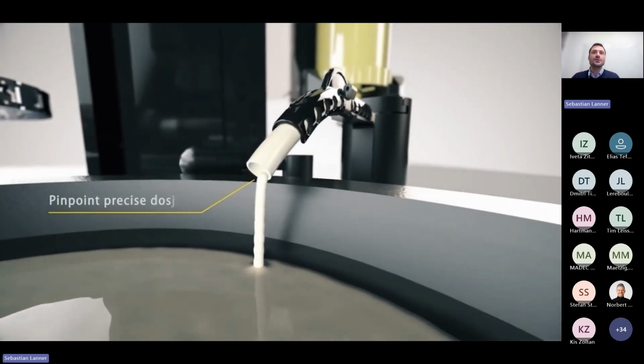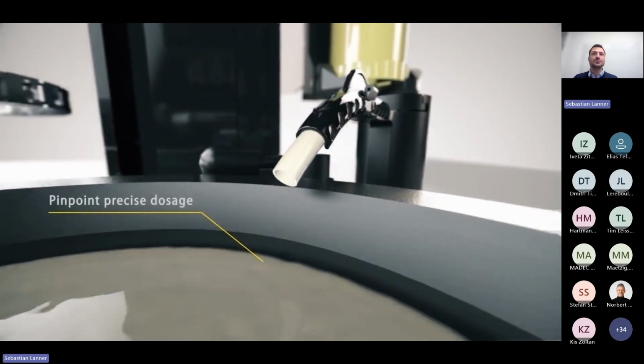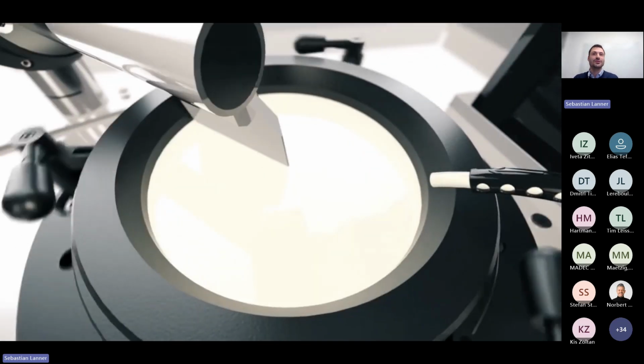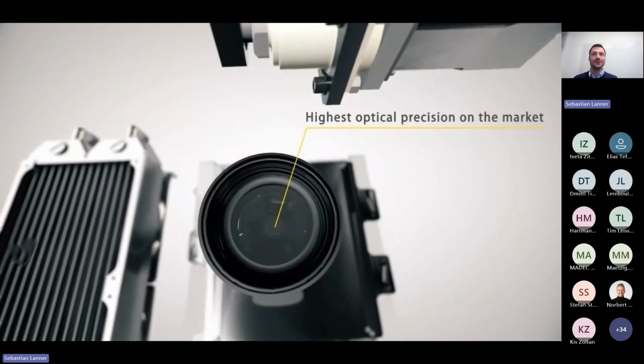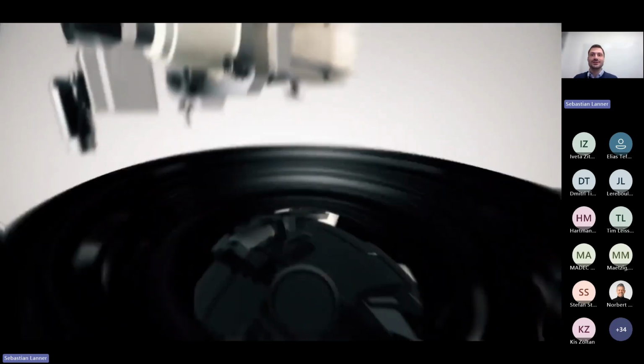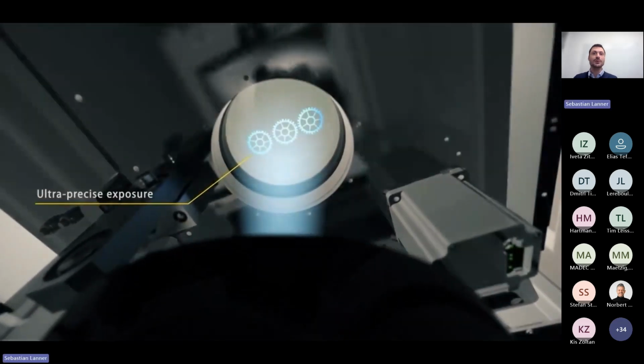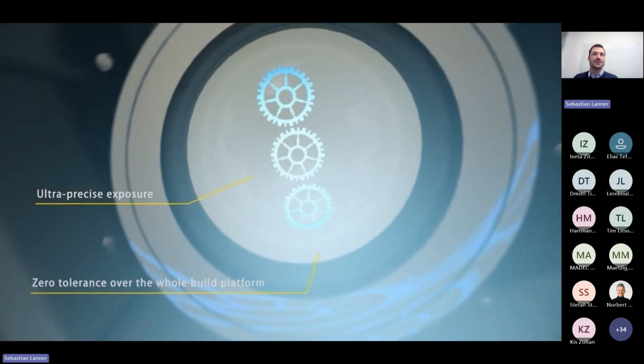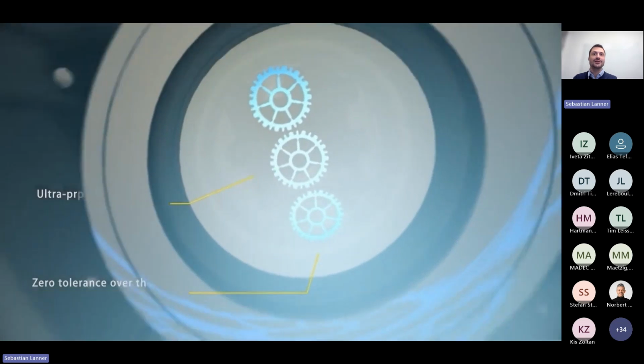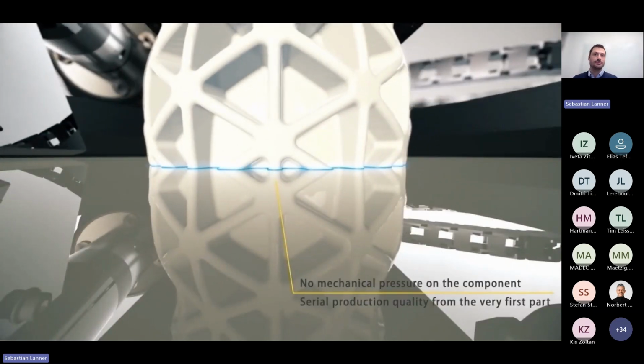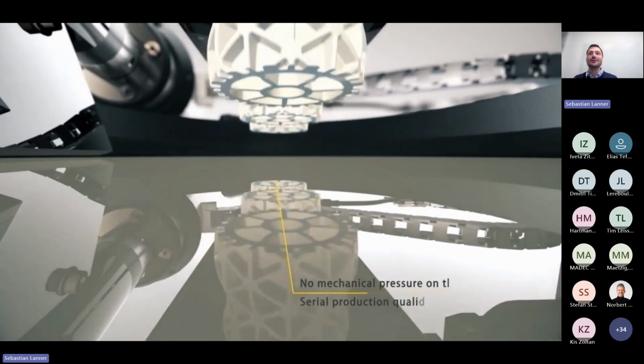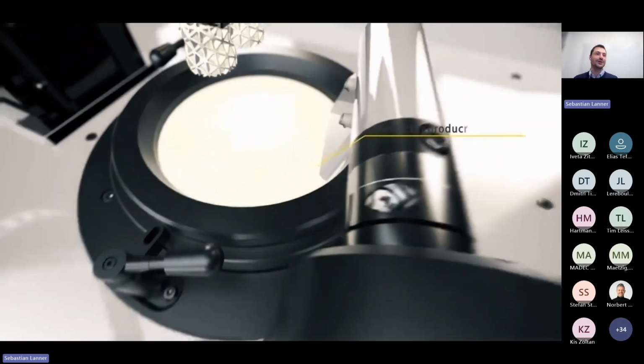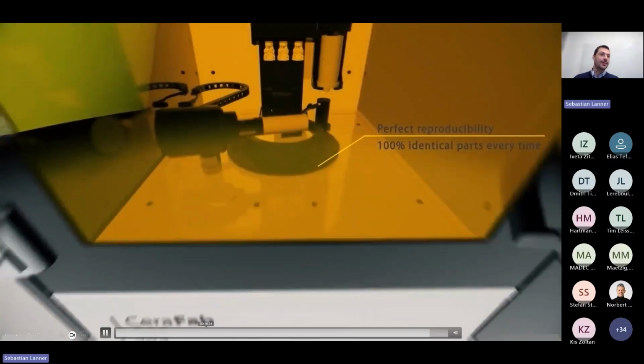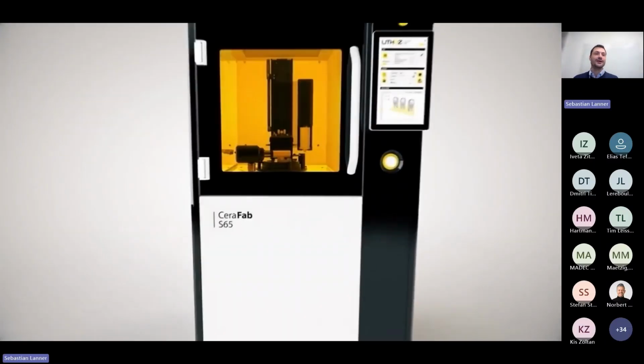We have an AI-driven dosing system that allows us to just use as much material as necessary in the print. So we have the rotation of the vat with the use of a vibroblade to create a uniform thin layer of slurry. We go through the slurry and come to the heart of the machine, the optical system. It is based on a DLP, and by using blue light, which is sent through the most accurate optical system in the industry, we create the layer image, which is projected on the bottom of the vat. This cures the slurry on the projected areas and makes it solid. By repeating these steps, layer by layer, we create the actual 3D printed part. And we're here again where we started and move on to the next slide.